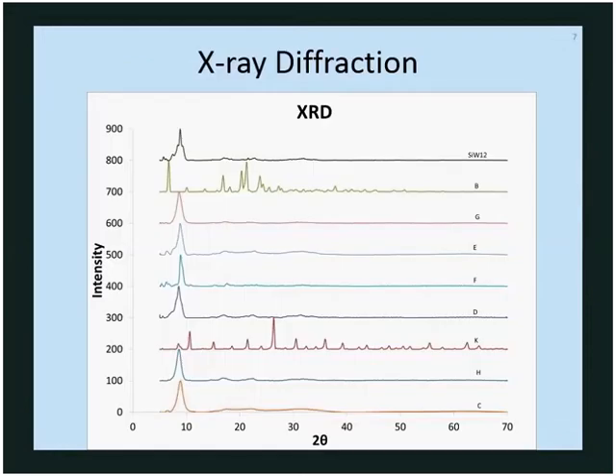X-ray diffraction was done on the dry powders, and comparing the dry powder of silicotungstic acid to the following ratios, you can see that the silicotungstic acid is present within the products, and that is seen by around 10 for a 2 theta value. This early 2 theta value indicates a longer distance between the atoms, indicating that the CTAB surfactant is doing its job at preventing agglomeration of particles.